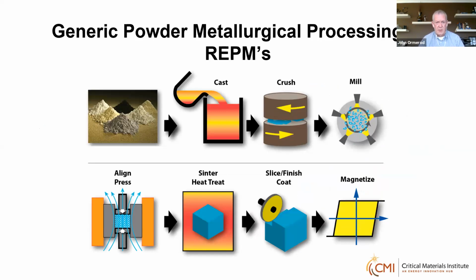We melt, typically under vacuum or inert gas. That alloy is then cast into some sort of form. That solidified material is then crushed to a coarse particle size. Those coarse particles are then milled to around 5 microns typically to form single crystals that can then be placed in a die cavity. A magnetic field is applied, the single crystal particles orient, and they're compacted in a press to form a green compact. That compact is then sintered to full density, typically heat treated to develop the final magnetics, and then they go through a series of machining operations to provide the required mechanical tolerances and shapes. And the magnets can either be magnetized at the magnet production facility or at the application, as they're either being built into the application or actually in the application.